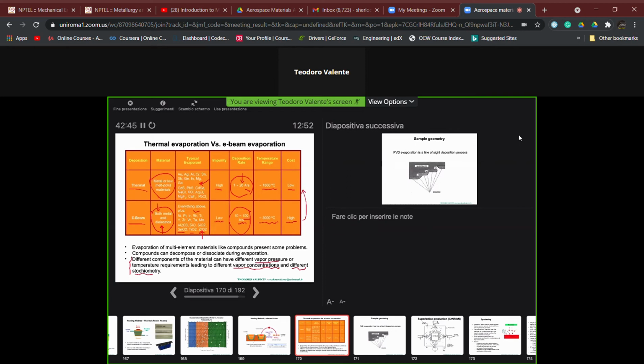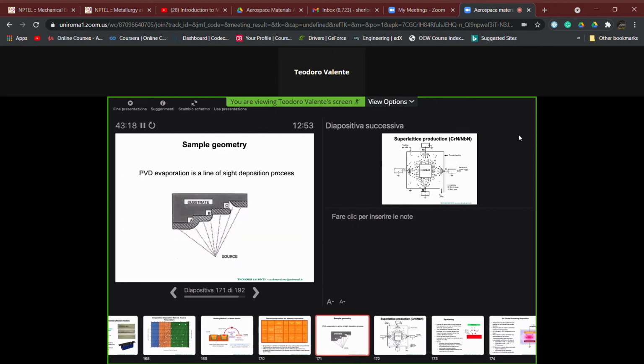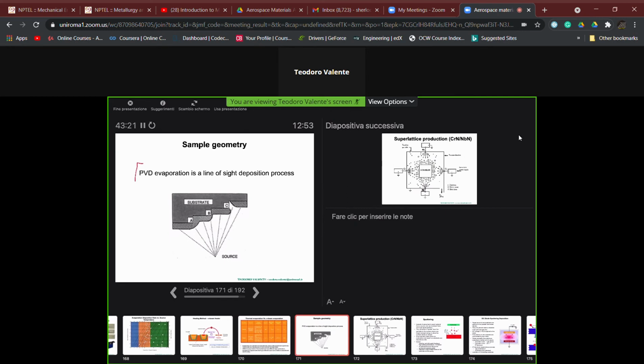That's the reason why this parameter has been considered in the general list of the important parameters for the thin film processes. And it must be seen if the final resulting composition can be considered suitable to the design purpose, because we can fabricate coatings not of pure elements, but of compounds, alloys, for example, having a final composition which is different from the starting materials. For both these processes, as well as I would say also for sputtering, which will be the next step, and this applies also to the thermal spray processing technology.